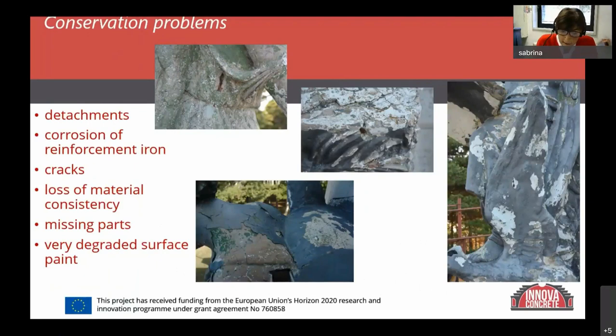The critical aspects for this monument were micro and macro fissures, in some cases with losses of cementitious materials, oxidization of reinforcing iron, and the results of bad maintenance due to the previous restoration interventions. Indeed, the application of layers of paint not compatible with the substrate and with each other caused over time an imperfect perspiration process, meaning a correct exchange between internal and external, and consequently an acceleration of degradation phenomena. You can see in the slide the difference, the layer of paint applied on the statue.